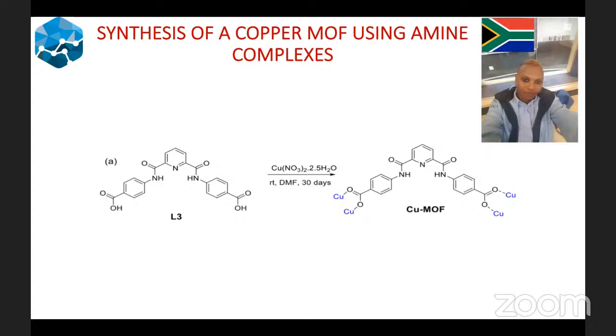Not yet. We haven't done those kinds of experiments. But what you propose, I understand that, and I think it must be possible. In our case, like I said, the solvents that we normally use for synthesis are the ones that coordinate to the copper, and we can increase the open metal sites by activation, by increasing the temperatures. We haven't done anything similar to what you have suggested.